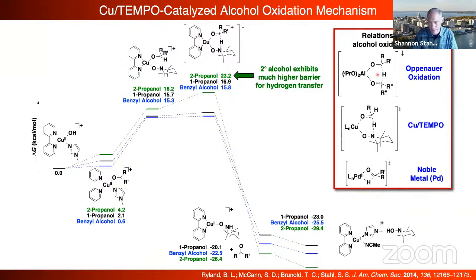It may be worth noting, this is basically like Oppenauer oxidation with a driving force, right? So the Oppenauer oxidation is just a Lewis acid that mediates hydride transfer between a ketone and an alcohol. Copper here is basically playing the exact same role as this hydride acceptor down here, copper and nitroxyl. The only difference is that now we've got oxidants involved rather than some thermoneutral reaction. It's also worth noting that this copper nitroxyl adduct is also playing the role of a 2-electron noble metal. So rather than doing beta hydride elimination to a single metal, you're now taking advantage of the 6-member transition state to do what is formerly a beta hydride elimination to this 3-atom fragment.